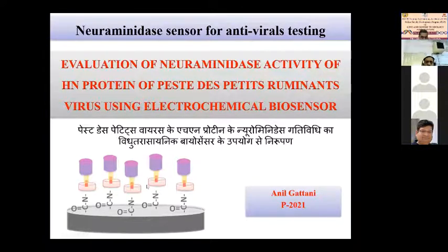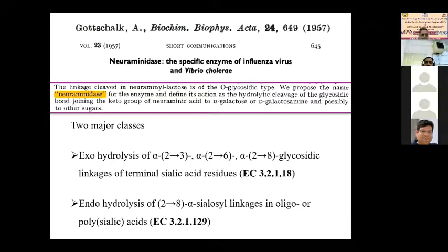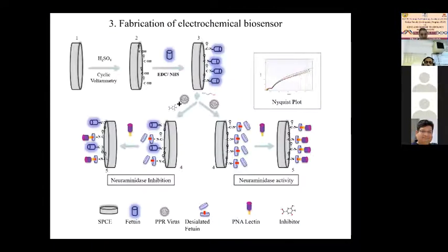This is the chemistry he did on that tiny black dot. He used the carbon electrode, which is a carbon paste, a graphite paste, and you cannot attach any molecules to it. So you have to make the carbon able to attach molecules. What we did was put sulfuric acid on it and activate it, creating carboxylic groups, by cyclic voltammetry in H2SO4.